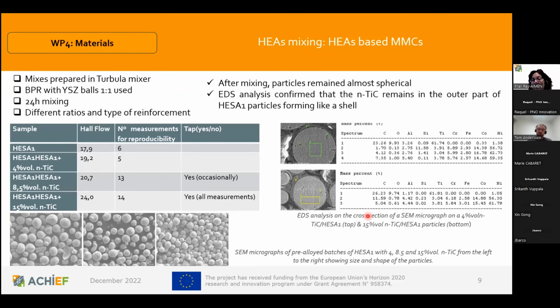Together with this, we prepared some mixtures, mixing one of the high entropy alloys with some nanoparticles in a Turbula mixer in order to avoid destroying the morphology of the particles. If you have a look here, you see that with nanoparticles, we still preserve the spherical aspect of the particles, and the powder flows quite well. We have some penalty on the flowability as we increase the percentage of the nano TiC, but in any case, they flow, and we were able to deposit some clads on the base material. When we look at the cross-section of the particles, we see that the nano TiC is attached, forming a layer, like a coating surrounding the particles. So it means that the nano TiC flows with the high entropy alloy.